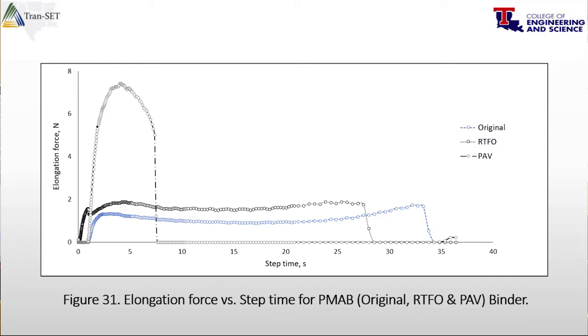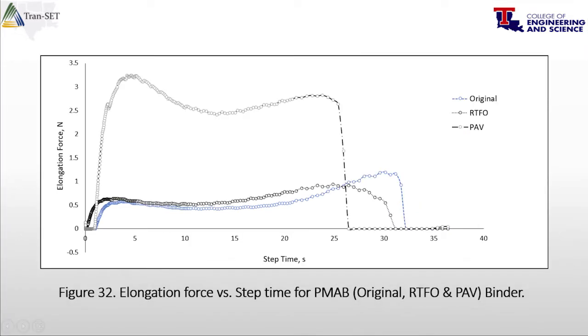And then this is the data at 40 degrees Celsius. So when you did that, we can see that this is the original binder, this is the RTFO aged binder, and the PAV did not show any second peak. In this case, same thing at higher temperature. This is the original binder, then the RTFO, and then the PAV.